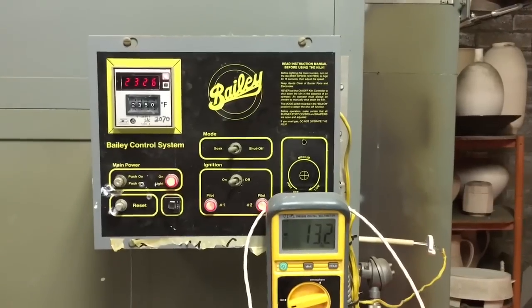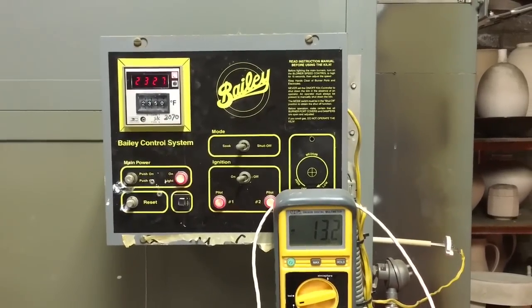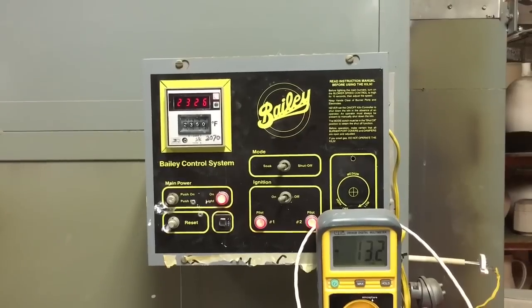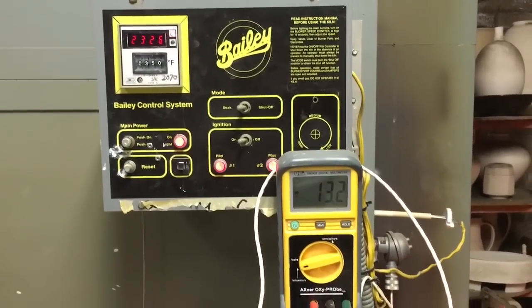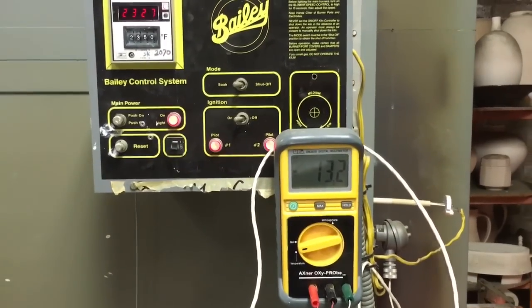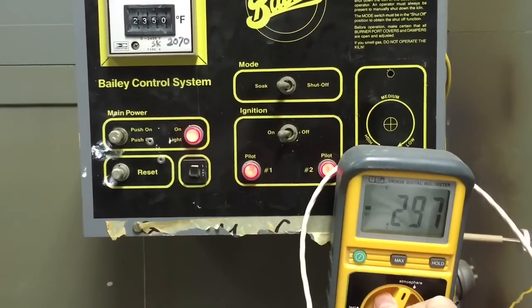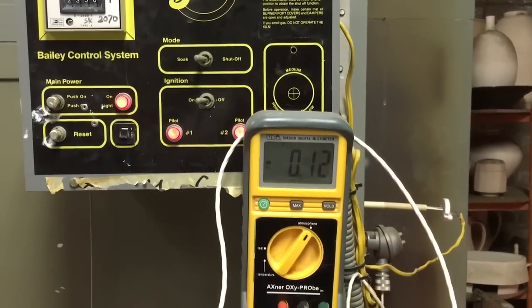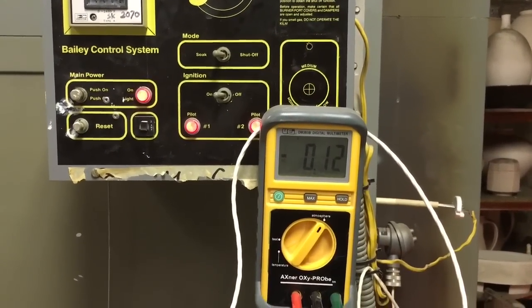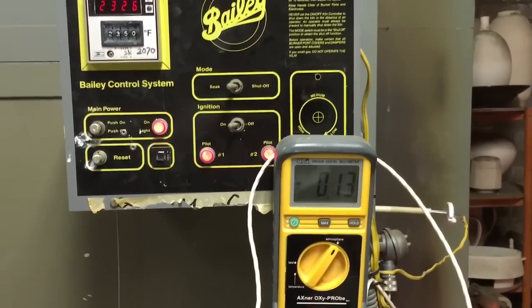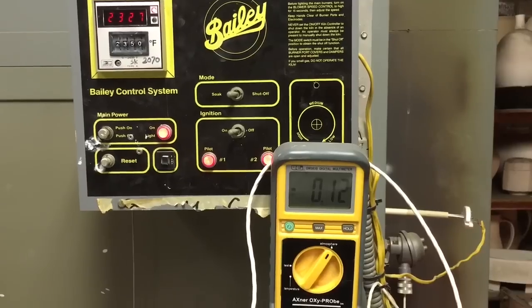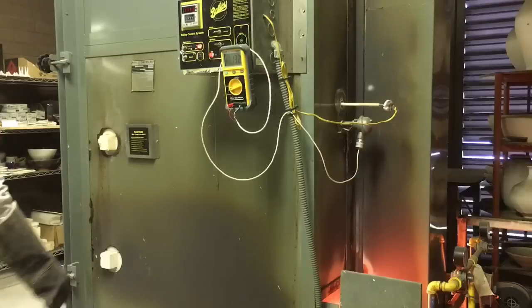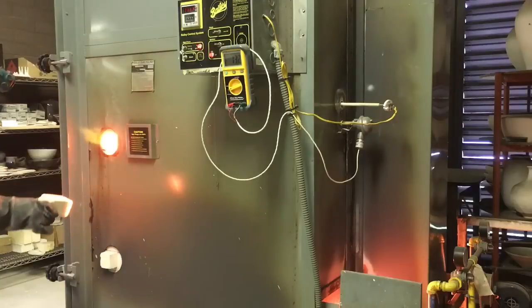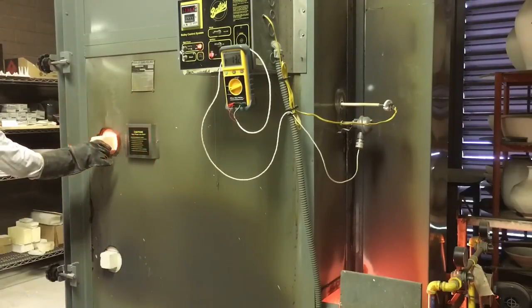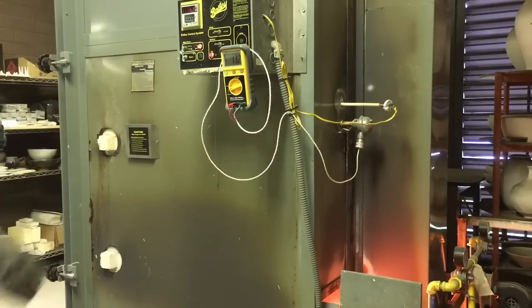The time now is 3 p.m. I'm checking back. The temperature is 2326. The reading on the oxygen probe is 13.2. And the atmosphere is almost the same, 0.11, 0.12, 0.10. It's kind of like an all-oxidation fire now. I just checked from the spy hole. I just found out that cone 11 is down and flat. So I'm ready to shut the kiln off.